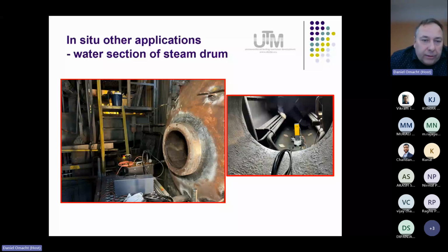The next example of using IIT, but not only IIT, was in the water section of a steam drum. The operator would like to know the mechanical and fracture toughness material properties of the inside part of the steam drum, and therefore we used our scooper. We scooped sample material from the inside of this drum. Subsequently, we did a small punch test plus evaluation of the microstructure and so on. And plus we made the IIT, and the clamping was done by a magnetic system, as visible in this picture.